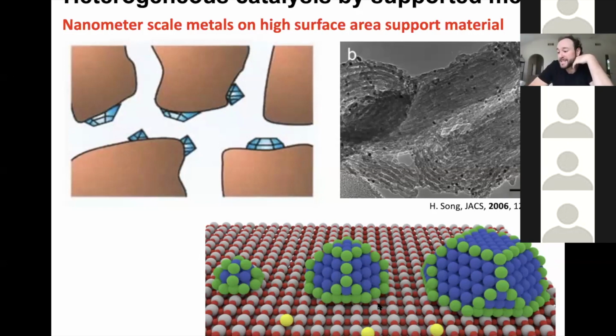If you take this even a step further, you can imagine these little yellow ones down here where you have single precious metal atoms dispersed on a support. Now, in this case, the local coordination environment is extremely different than you would find in a larger metal particle. So you're bonding to oxygens or metals on the support rather than neighboring metal atoms. And so as a result, you could imagine that the oxidation state of this species may be different than these. The coordination environment would tell you that the reactivity should be different. And of course, if you have a reaction where you need communication of multiple sites, this will happen very differently on this sort of site than it does on this sort of site.